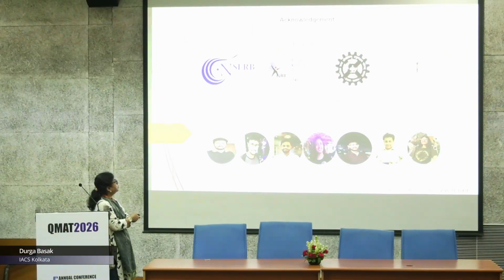So here we have compared different photo response parameters, and if you look at this table, you can see that the responsivity, detectivity, response time, in all respects the microflake is better. The better properties in microflakes are probably due to the lesser electron-phonon or exciton-phonon interaction in microflakes because of dielectric screening.